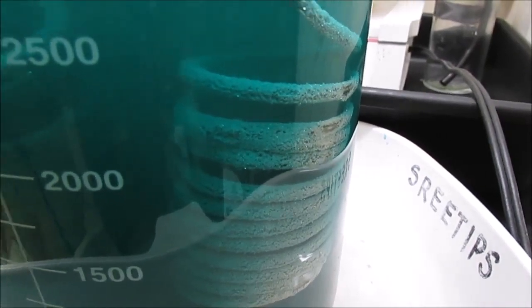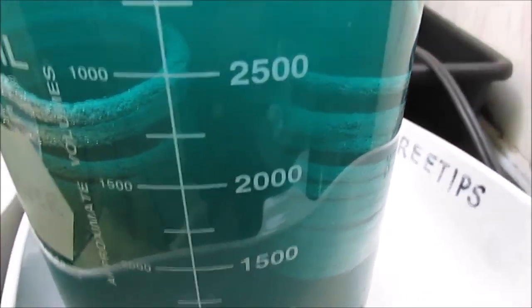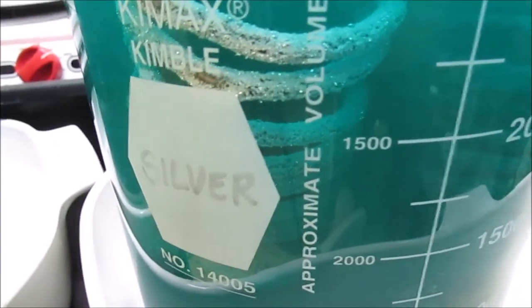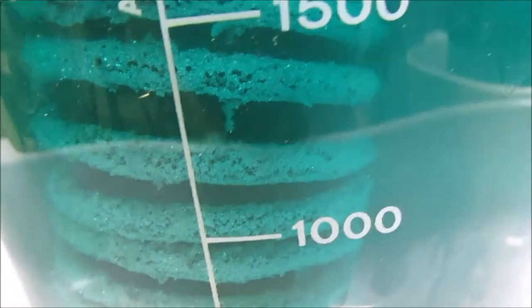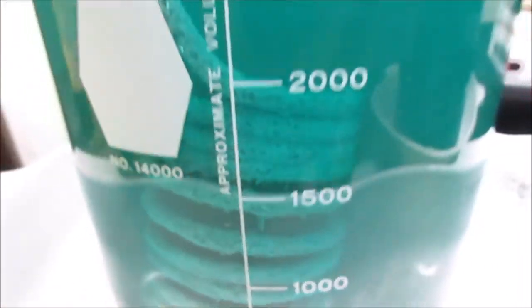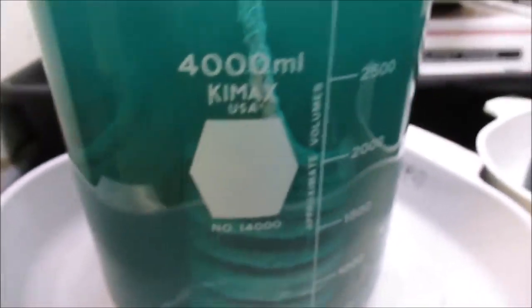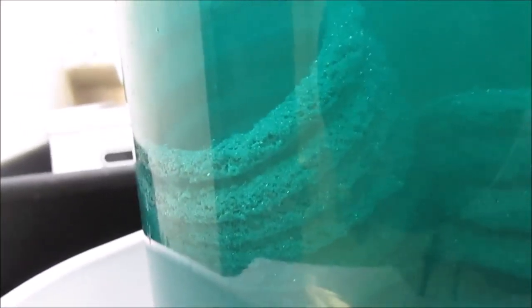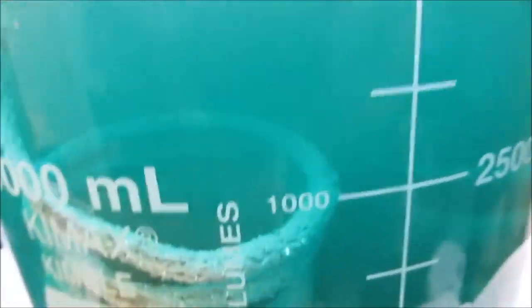It's been about 5 minutes since I added the water and the fresh copper coils there, and everything seems to be moving nicely now. I had to get everything adjusted correctly in order to make this reaction take place properly. It's a good thing we've seen that on the video here. Shows you what can happen if your solution is over concentrated, or if you get a passive layer formed on your copper coils.